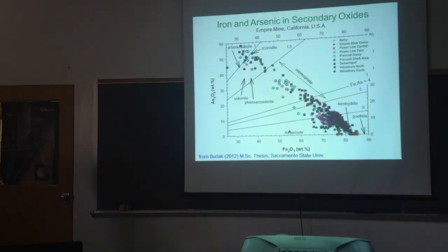And so she did some quantitative work showing that the weathering products have a higher arsenic to iron ratio than the original material. I won't go through this in too much detail, but we had a slope of about 2 to 1. Weathering products had higher arsenic to iron ratios than the original material. These are some microprobe data that she generated that show the iron content on the horizontal axis and arsenic on the vertical axis. And we see this continuum I mentioned between goethite and ferrihydrite, which are the pure hydrous ferric oxides, and this amorphous ferric arsenate, which could be the mineral scorodite, as well as crystalline. And so this material in between here, we consider the hydrous ferric arsenate. So this is the HFO and the HFA, but it is kind of an arbitrary distinction. We have a continuum between these, and it might represent a really fine nanoscale mixture between these very poorly crystalline components. But the majority of the materials are down here.